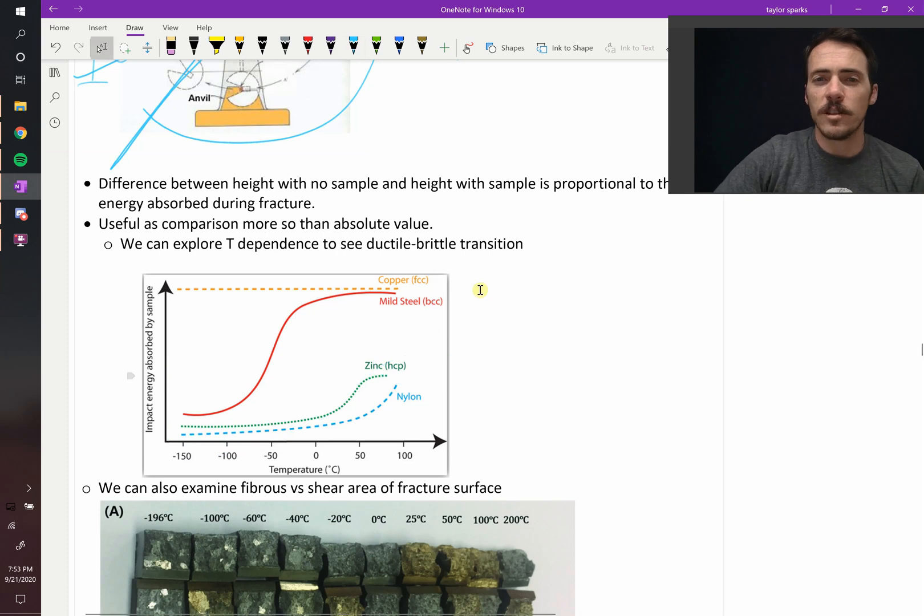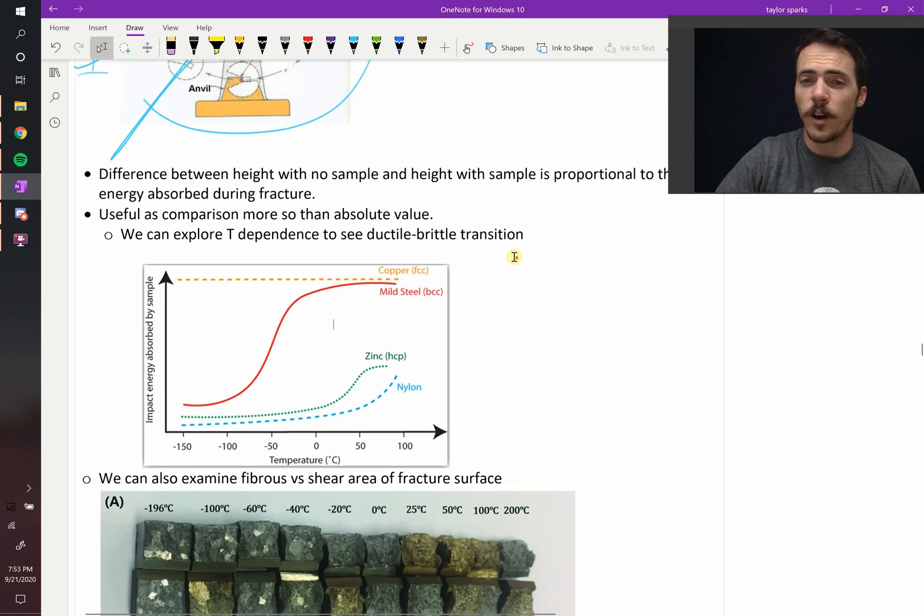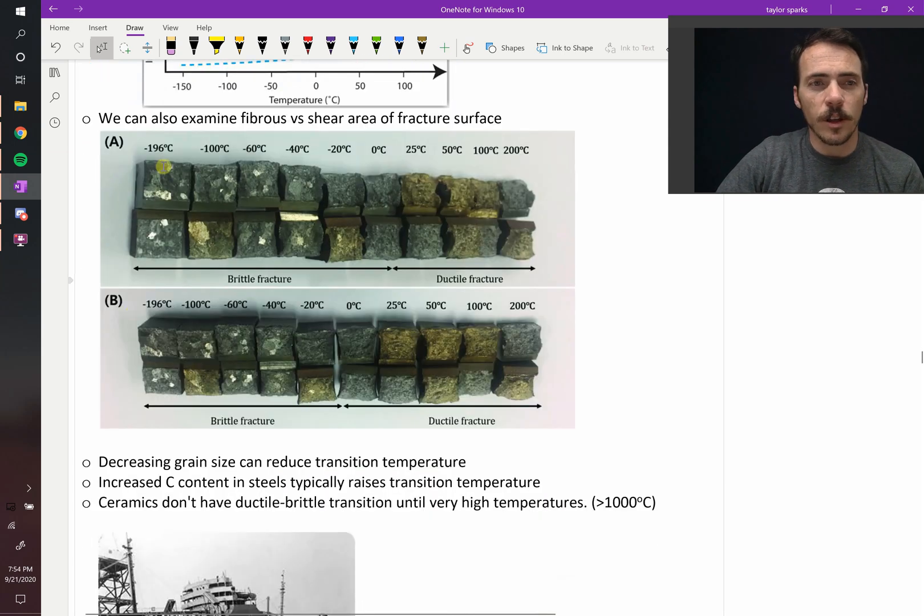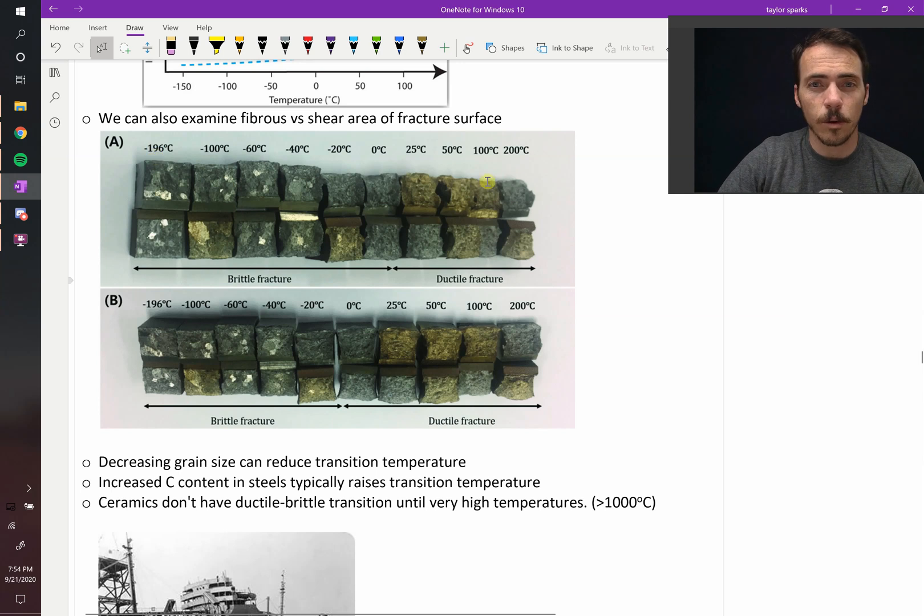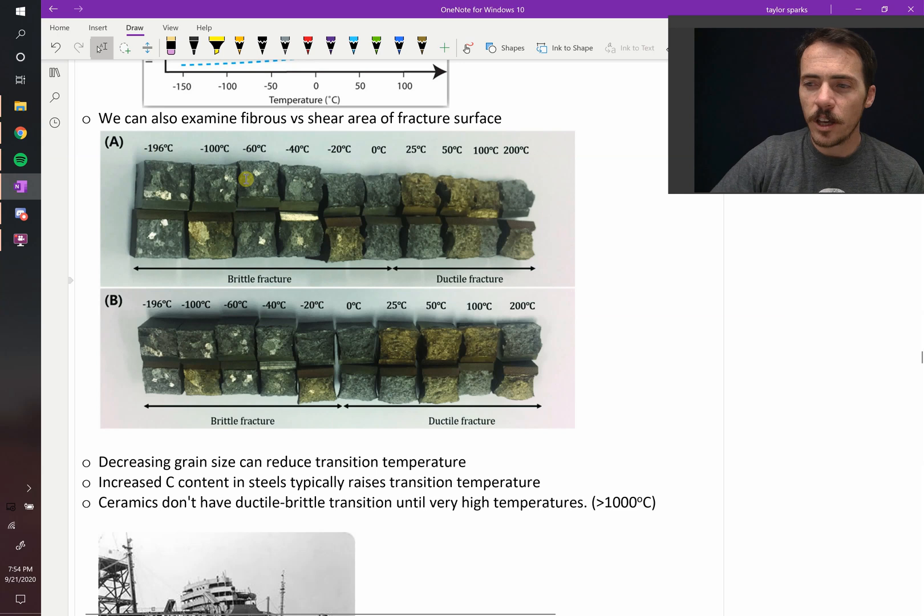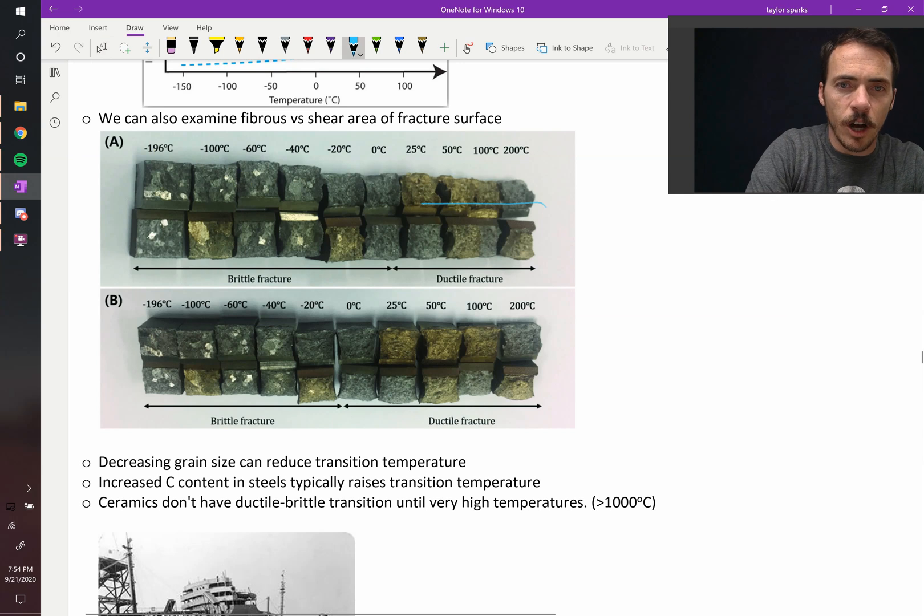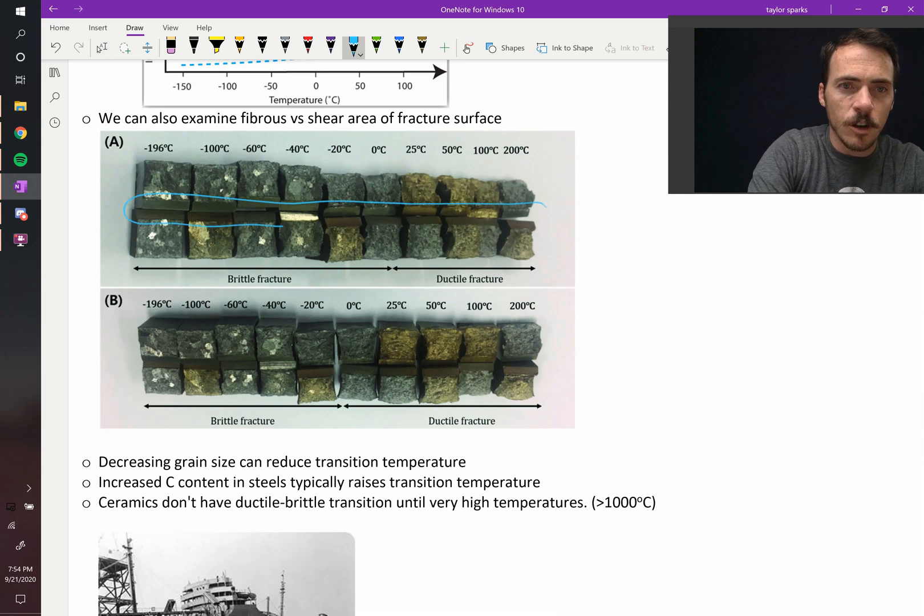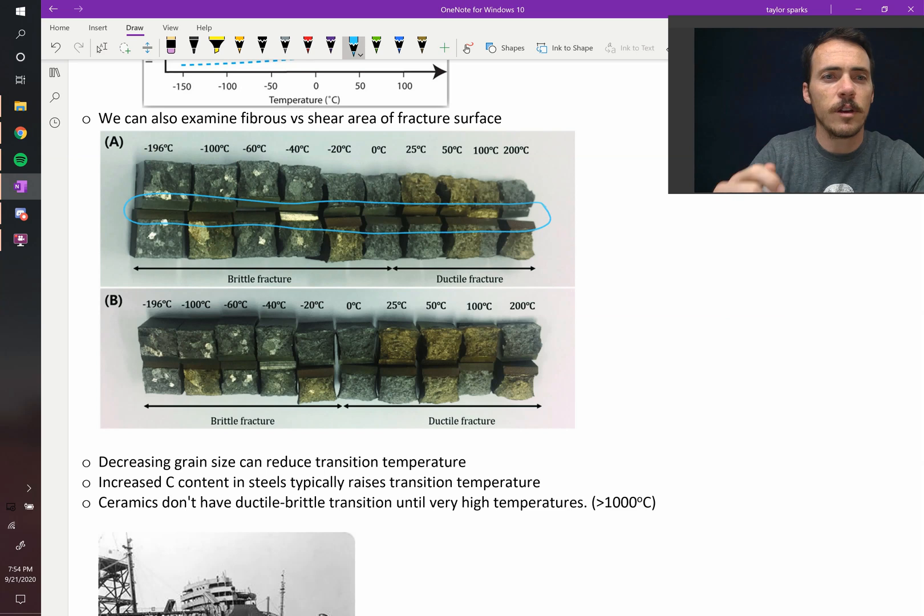Another way to see this is if you were to look at the fracture surfaces using fractography. Take a look at these samples, samples A and B. As you start at very low temperatures, negative 196 Celsius, and then you slowly warm it up, take a look at how the fracture surface looks different. In each case, you've got your notch. This is the notch that was there initially because they put a little notch in it to start with.